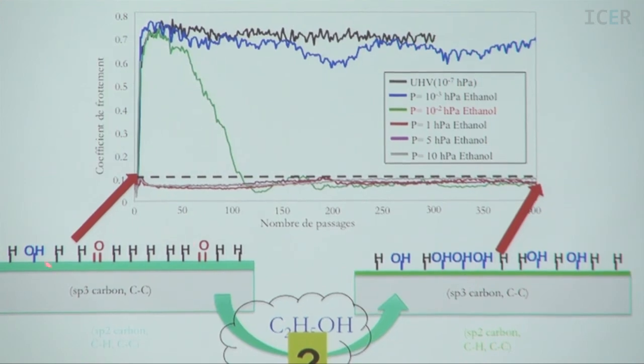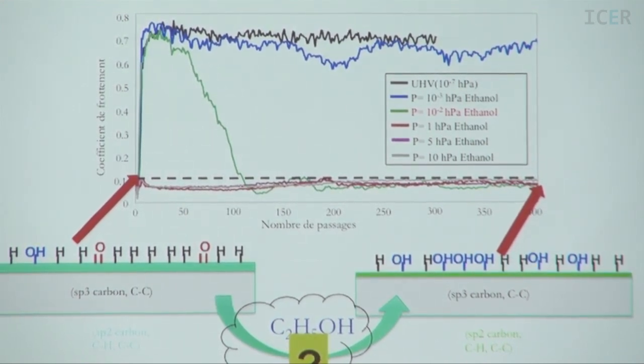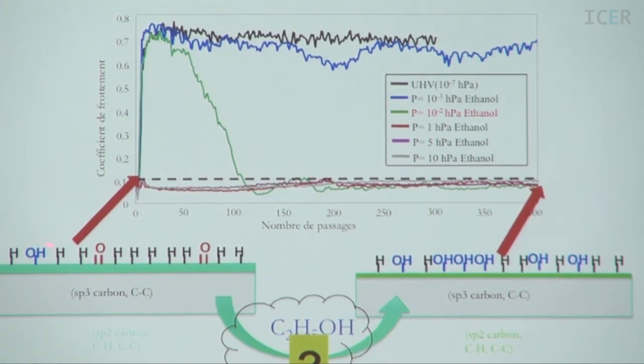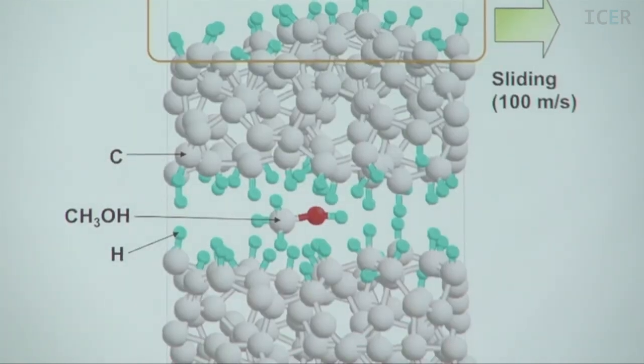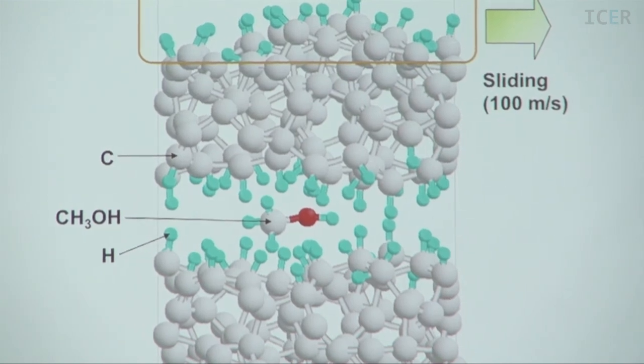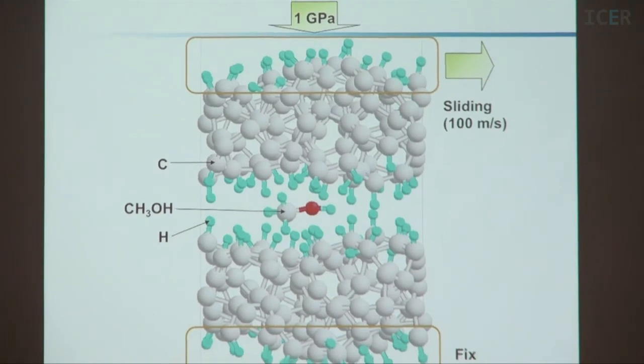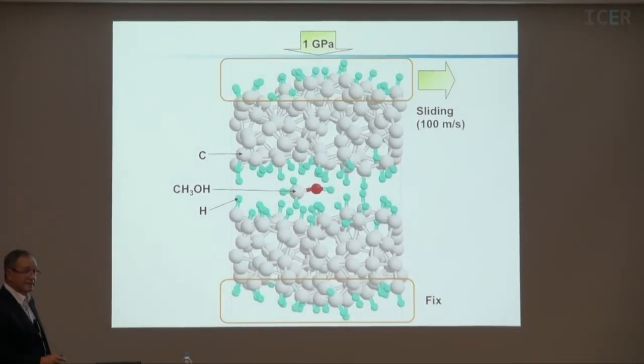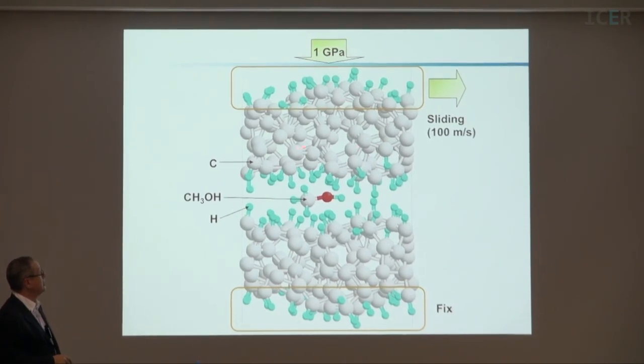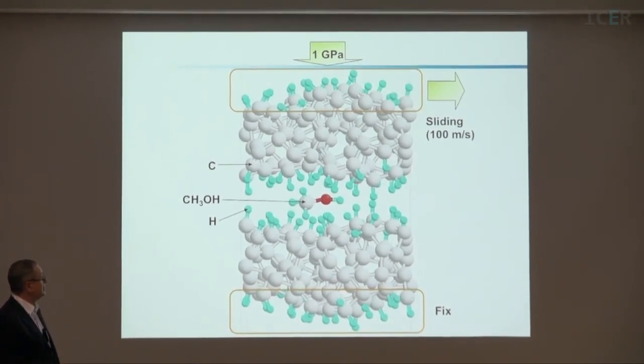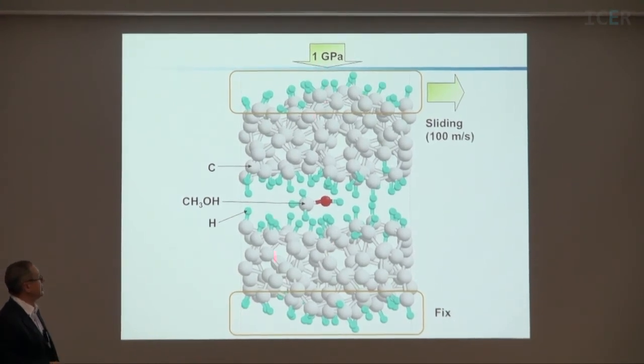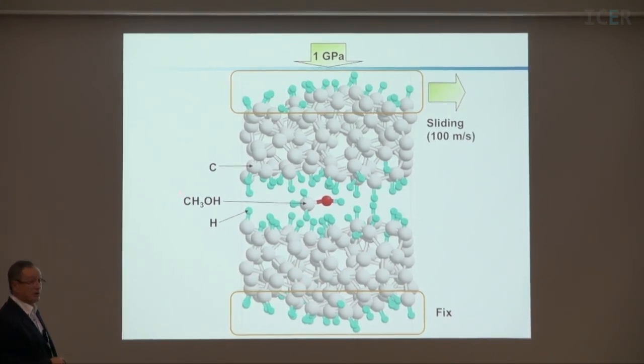So we suspect that after this, the reaction with ethanol gives this. We suspect this. And this lubricates, and this does not lubricate. But of course, this is very difficult to analyze. So again, we use computer simulation. This computer simulation was made by Professor Kubo in Sendai. So this is a modelization of the carbon here and the second carbon. The high pressure between this and this, 1 GPa, sliding, and putting a molecule here of methanol.